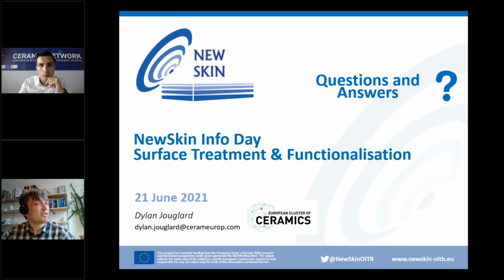Thanks. The trouble is that when I was talking about coatings, it's typically below 2 nanometers. So if the tool or part surface is very rough, then the coating will not survive because there will be too high local stresses.